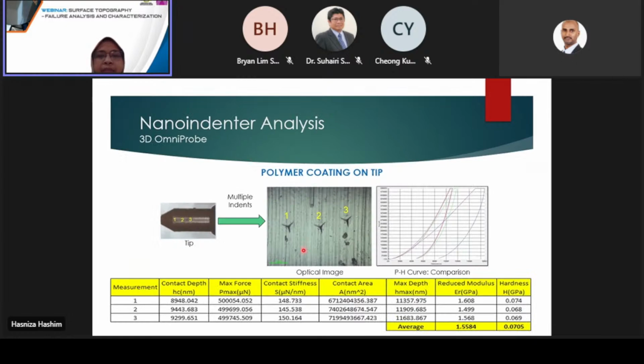And this is another example where we did the indentation on the tip samples. As you can see here, the surface of the tip is not really flat, but there's some area that is flat. So what we have to do is put some resin at the bottom of the sample to make sure that the sample does not move. Then after that, we use super glue to paste the samples onto a clean wafer, and then use the vacuum chuck to hold the sample.